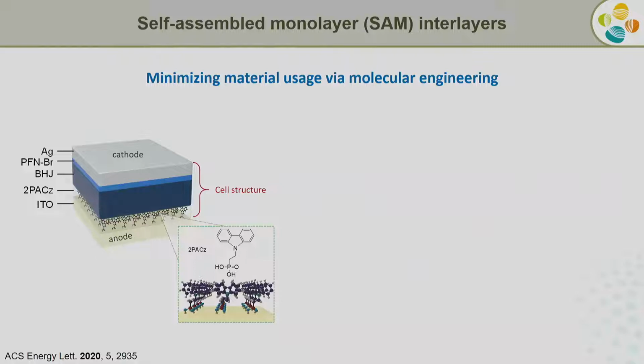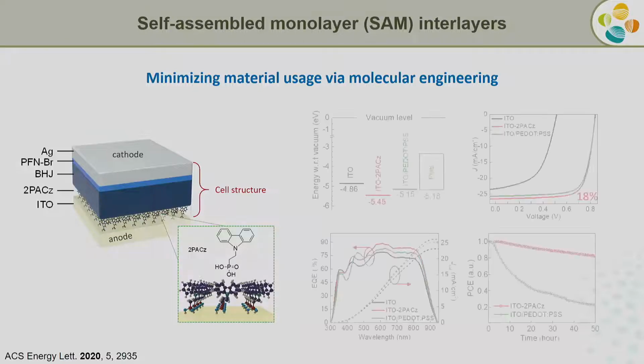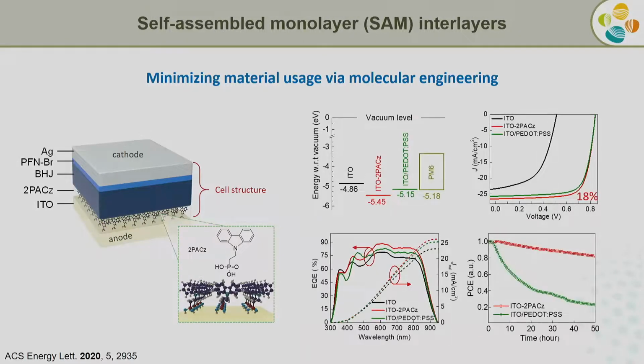So essentially, we have managed to replace the traditional hole transporting layer, which is typically 30, 40 nanometers thick, with something which is 1 nanometer. So essentially minimizing the amount of material used by a factor of 30 to 40. Plus, we have been using nature for this self-assembly. We don't use sophisticated equipment to grow this material where we want it to grow. And using this self-assembled monolayer as the active components, we've been able to make solar cells which are 18% efficient. So essentially 18% of the power from the solar spectrum can be converted to useful electrical energy.